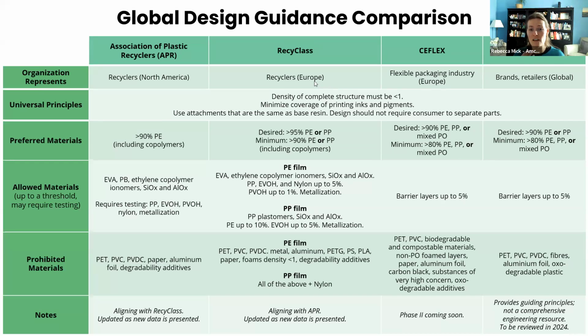All right, so we have a few things that need testing for APR. That includes polypropylene, EVOH and PVOH, and nylon, which are all barrier materials. So there's no specific guidance around those yet from APR. You'll just need to go through, again, the critical guidance testing that Paul mentioned to make sure your structure is compliant for those materials. For Recyclass, it's a very similar list, as I mentioned, with the change that polypropylene, EVOH, and nylon have a limit, right? So they're acceptable up to 5% without any kind of testing, and PVOH has a limit of 1%.